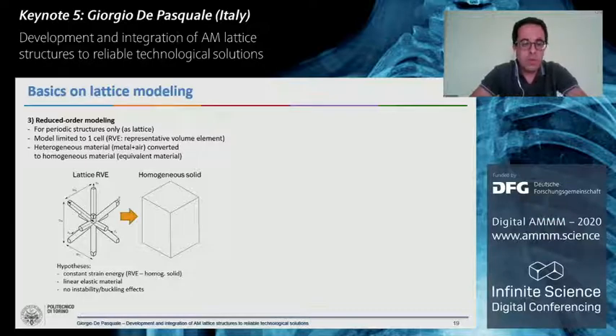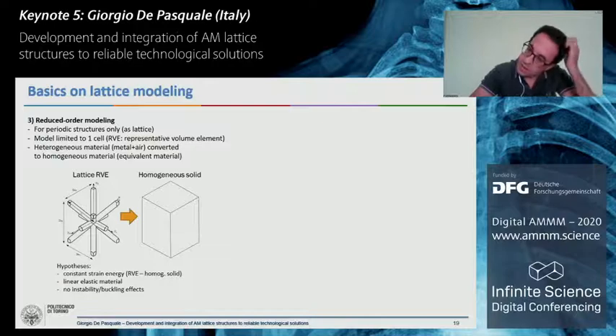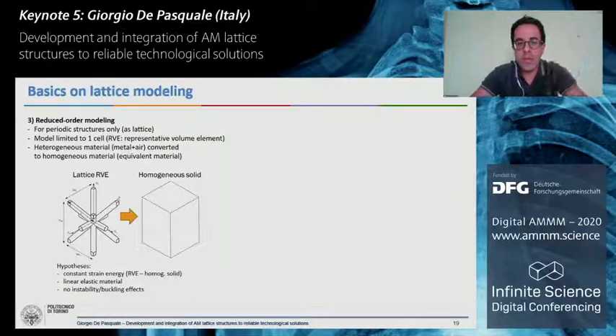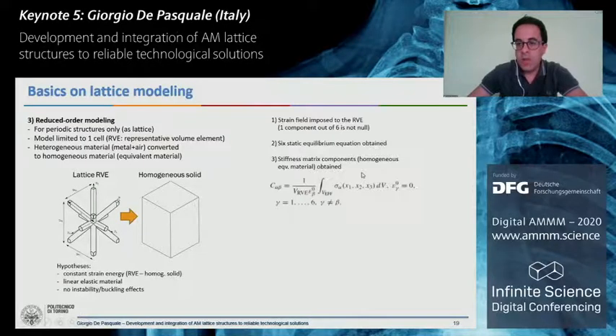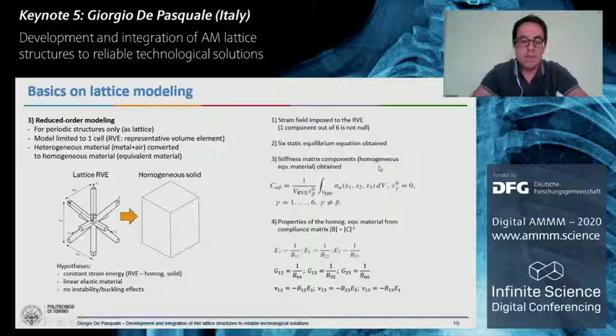The alternative, that is the best way in our opinion, is to use different models that are reduced order models, for example the homogenization method, where you can replace the complex shape of your lattice cell with a homogeneous solid with very simple geometry that has the same mechanical and structural properties of the real lattice shape. There are well-known methods to do this transformation under specific hypotheses. Basically, we can impose a strain field on the representative volume element, that is our cell, to write 6 equilibrium equations and to calculate the stiffness matrix of our element. Then, by calculating the compliance matrix, that is the inverse of the stiffness matrix, we can simply calculate the Young modulus, shear modulus, and Poisson coefficient of our element.